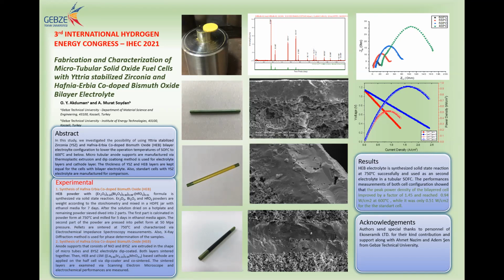You're seeing the yellow layer on the tube. It is unsintered because I couldn't share the sintered one; when we sinter it, it's so thin and it's transparent, so we cannot see if there is a layer in there from this picture. And then we coated the cathode and measured.